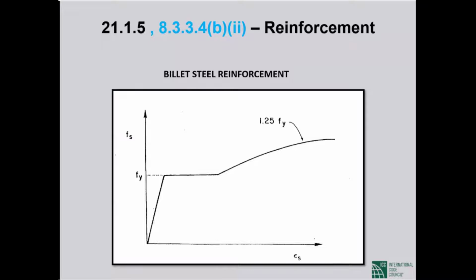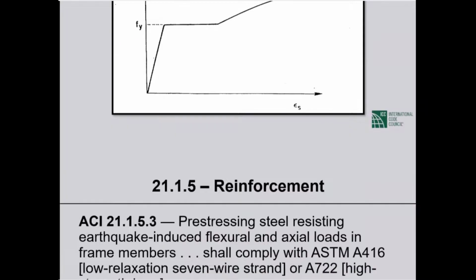This requirement has kept a lot of foreign steel out of the US market. I know that many foreign reinforcing bars cannot meet this requirement of actual tensile strength to specified yield strength of no less than 1.25. I do not know the situation in Bangladesh, but this is a requirement. In the US today, for high strength reinforcement, particularly in ACI 318-19, the 1.25 requirement has been relaxed, but I need not go into that today.